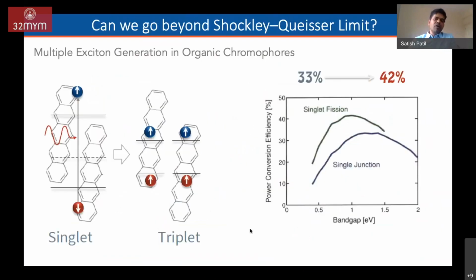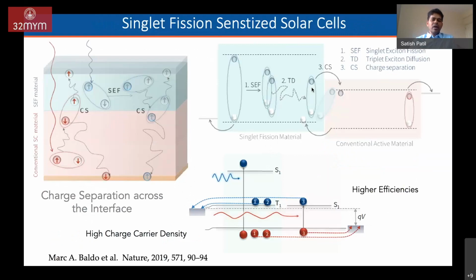So yes, one can go beyond the Shockley-Queisser limit, if you generate something called multiple exciton generation, multiple excitons in an organic semiconductor. These are some preliminary results. You see that in theoretical calculations for single junction solar cells, you get a maximum efficiency of up to 33%. As I highlighted in the previous slide, when you use a concept like multiple excitons, the efficiency can go from 33% to 42%. So what is this multiple exciton process all about? This is something we have been working on at IISc.